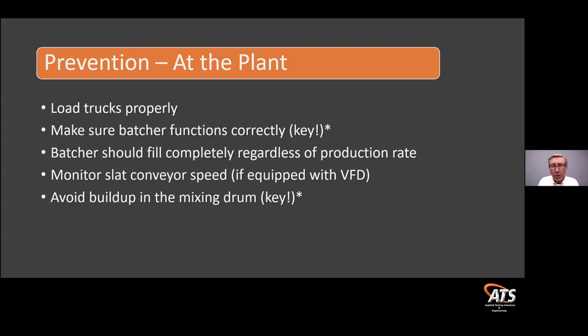This would be the other 20% usually at a plant. Now, these percentages are not firm, but when a guy tells me he's got a batch segregation, he thinks it's plant induced. Since I'm the plant geek, I'm like, look at your batchers first, and then see if you've got buildup in the mixing drum or the mixing chamber, or as Steve said, the chute coming out of that device. So any dam that gets created in the mixing device,